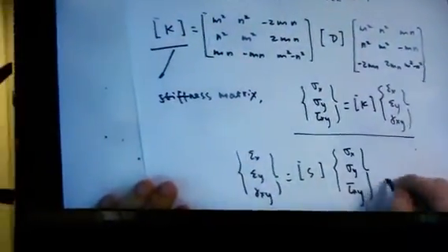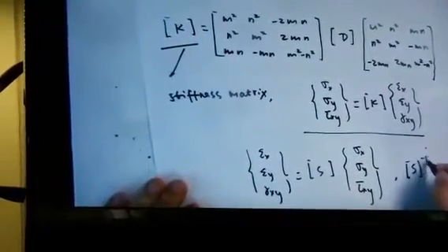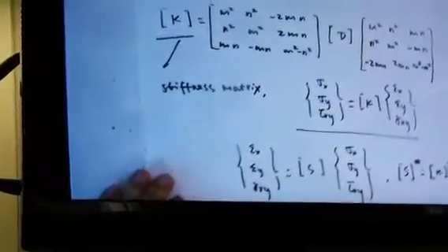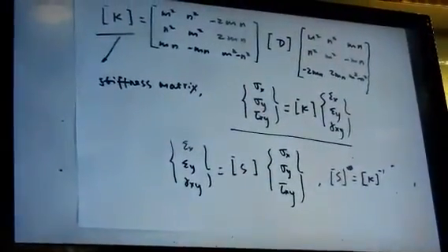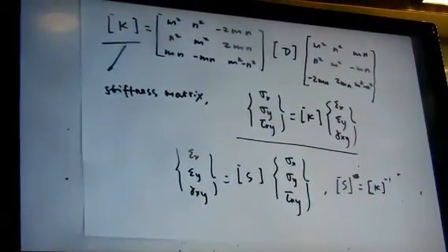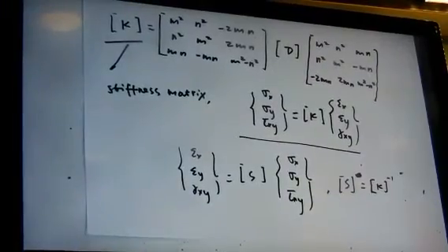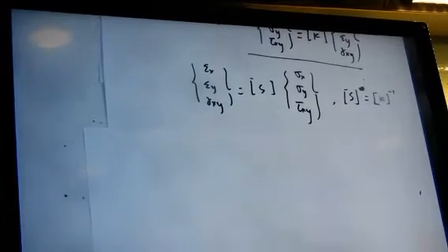tau xy. And this matrix can be the inverse of this matrix. In the textbook, they also have the formula for you already. You can write down that formula for your calculation, or you can do this inverse during the homework or exam. It's up to you. So this is the definition of the stiffness matrix and the compliance matrix for the generally orthotropic composites. When we have those two matrices, we can calculate the deformation of the composites. When you apply a loading on the composites, what is the strain along three different directions.